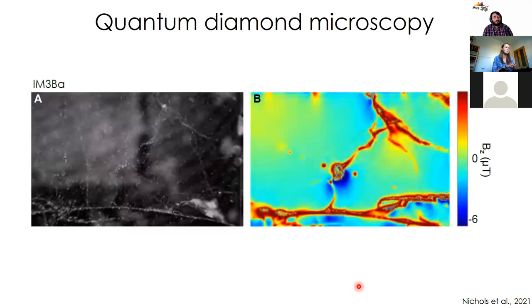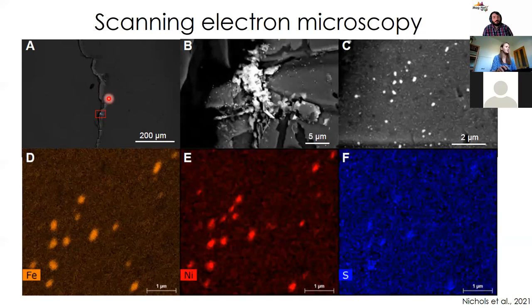And so we used the quantum diamond microscope at Harvard just to have a quick image of the heated olivines, and we found what we expected, that the magnetization is focused along the cracks. When we zoomed in on the cracks using the SEM, we find that they're packed full of these little iron nickel grains. So we're basically cooking in ideal paleomagnetic recorders because the conditions are too reducing. And this is the compositional map showing that it is basically an equal amount of iron and nickel and not much sulfur. So the controlled atmosphere experiments work very well.